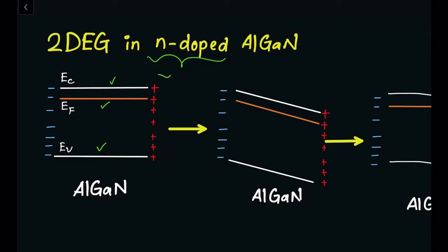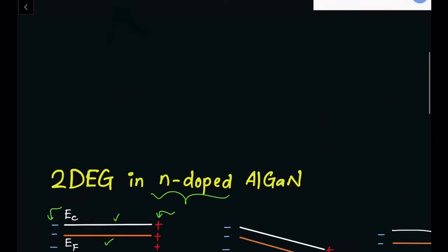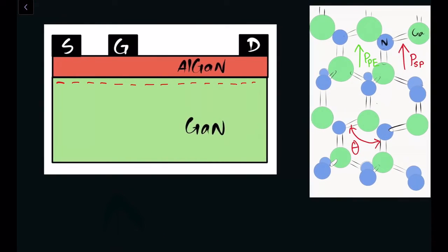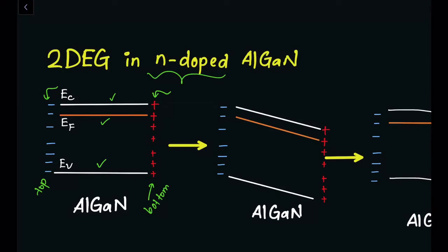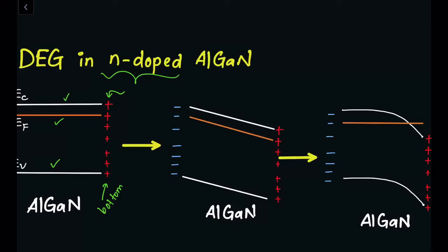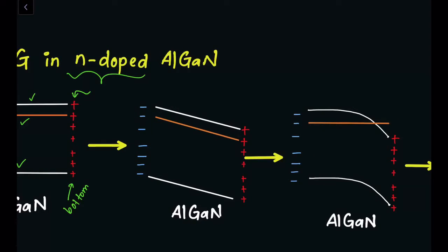We also see some positive charge and negative charge at the surface. At the top surface there are many electrons and at the bottom surface there will be a lot of positive charge. Remember these are bound charges like a dipole, created by the polarization vectors already shown. They are also present in the aluminum gallium nitride as well, because the AlGaN is placed on top of the gallium nitride crystal and their lattice structures are not matching. That's why the gallium nitride will insert some tensile strain on the AlGaN and that's why there will be piezoelectric polarization because of that stress. When there is a polarization vector or electric field in this crystal, it will create band bending — that's well known from Poisson's equation.